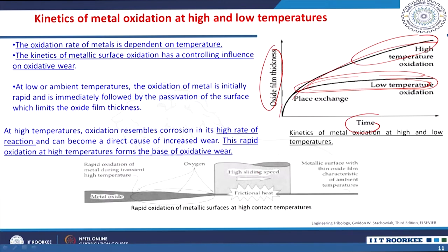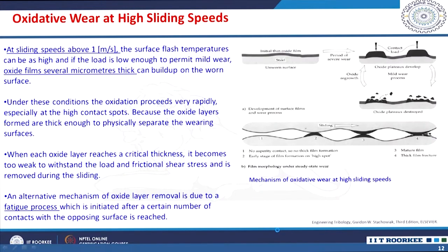So, you will have high sliding speeds, and that leads to very high frictional heat, which leads to high temperatures at the contact. You will have the metal oxide thickness also increasing. So, rapid oxidation at high temperatures forms the basis of oxidative wear. With respect to sliding speeds, at sliding speeds generally above 1 meter per second, the surface flash temperatures can be high, and if the load is low enough to permit mild wear, oxide films of several micrometer thickness can build up on the worn surface, right? Under these conditions, oxidation proceeds very rapidly, especially at high contact spots.